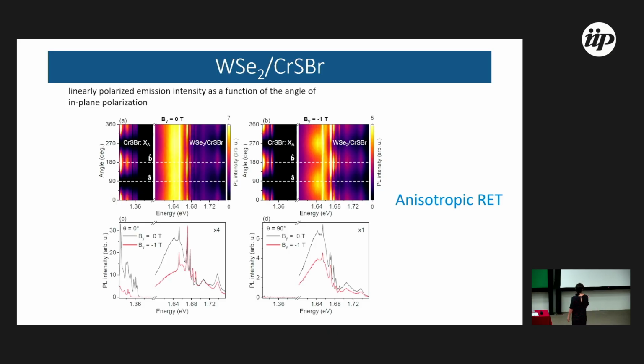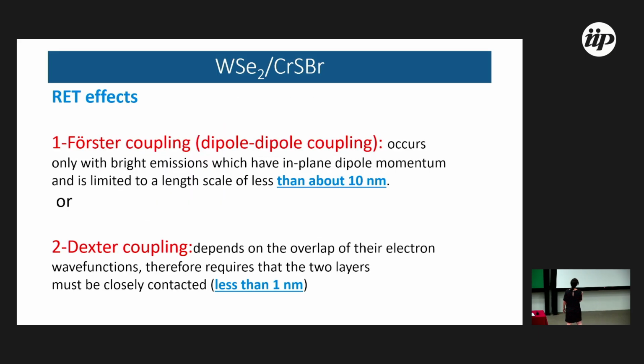And one thing before I finish, this energy transfer is anisotropic because CrSBr is anisotropic. We can show that this effect occurs only when you detect aligned to the B exciton. If it's not on the B exciton, you don't have this enhancement of intensity. So it's resonant energy transfer anisotropic because the CrSBr is anisotropic. This was observed before with black phosphorus, that is anisotropic, with another material. People have seen this, so this is expected, but we show this.